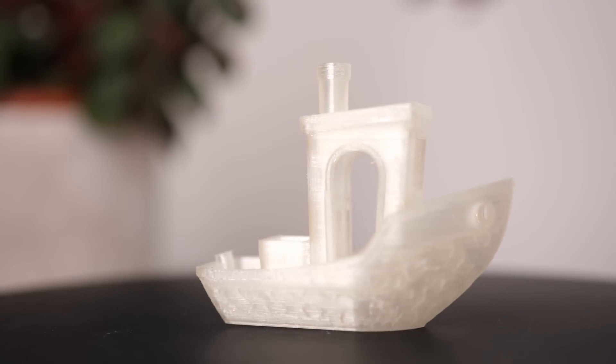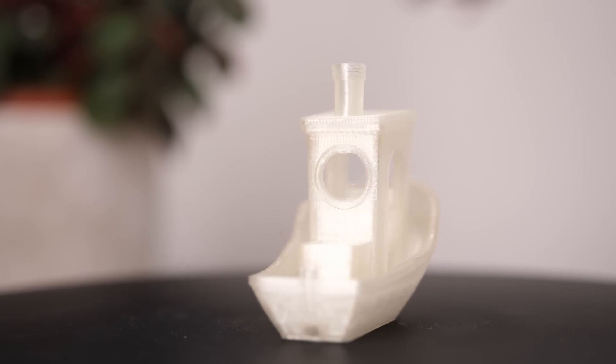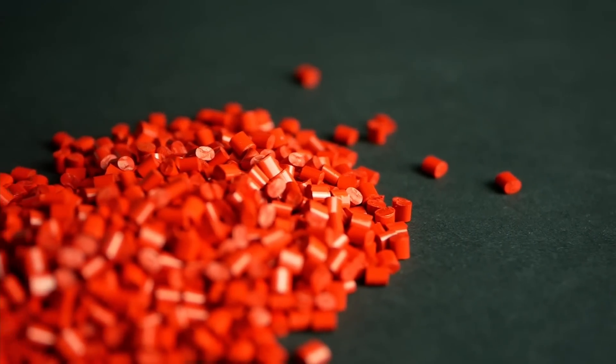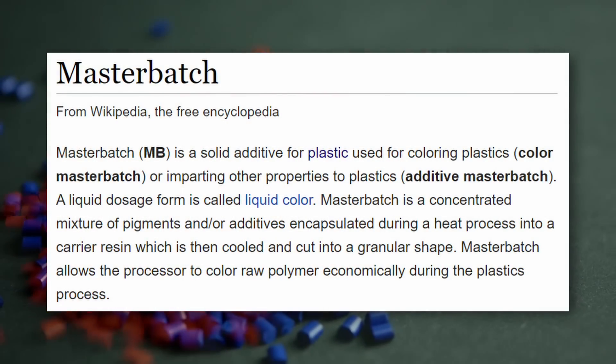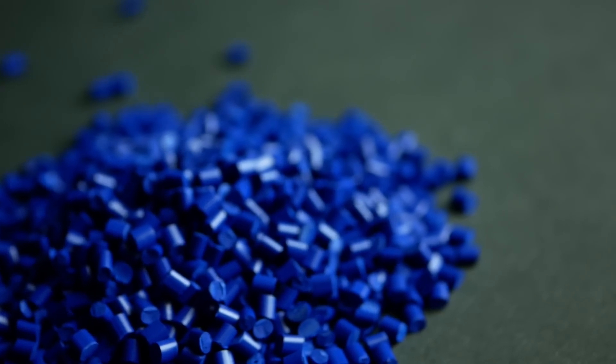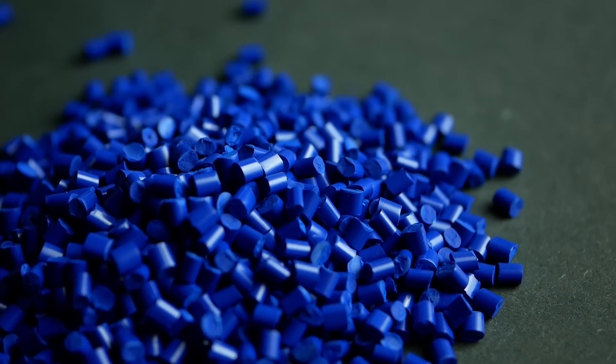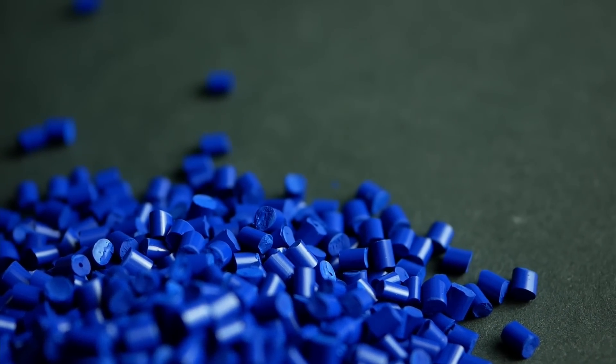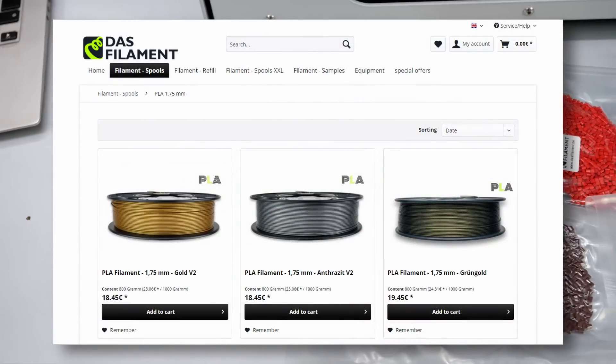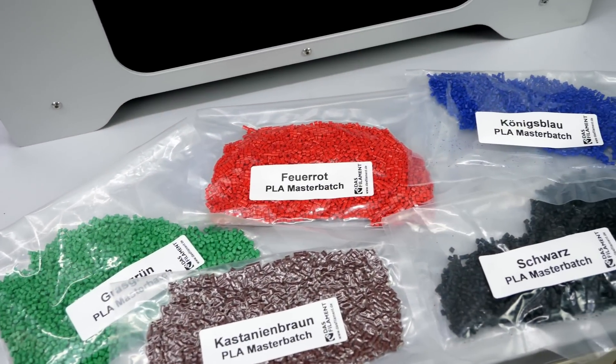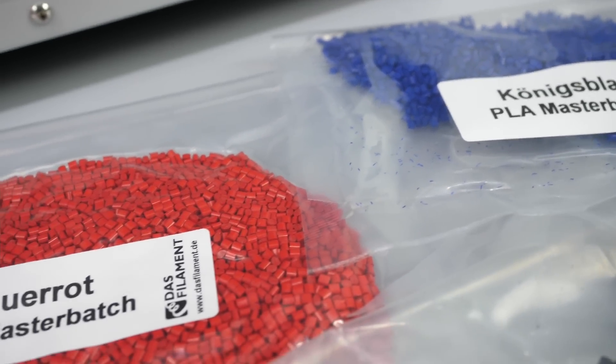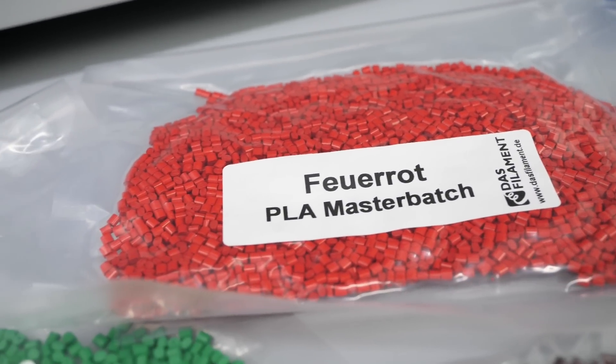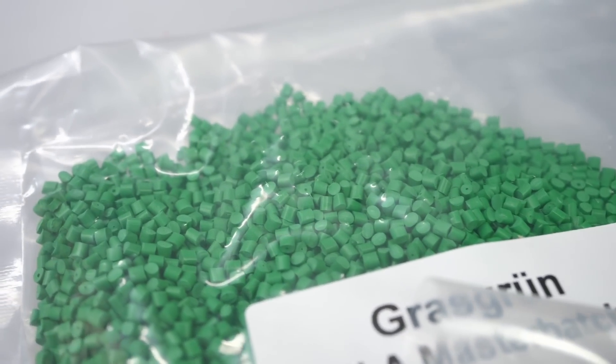Transparent material is nice, but honestly, because the prints always turn out not perfectly clear, we rarely print with such a material. This is where color comes in. Coloring plastics is usually done with a so-called masterbatch. A masterbatch are pellets of highly concentrated pigments held together mostly by the same or a compatible polymer that you are processing, just a more manageable and more controllable way than mixing powdered pigments with your pellets before the extrusion process. My friends from Das Filament, a German filament manufacturer from which I buy most of my PLA and PETG filament, were so kind to send me a bunch of samples to play around with. Since you're usually only adding 1-5% of the masterbatch to your normal pellets, I only needed a couple of grams that I'm sure the masterbatch manufacturers would not have been happy to sell me.